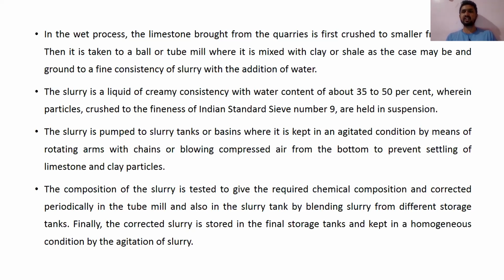Okay, the liquid content in the slurry will be more than the paste. You can understand what I mean to say is slurry. The slurry will be prepared by addition of water into the mix of limestone and shale or clay. Then the slurry is a liquid of creamy consistency with water content of about 35 to 50%, wherein particles crushed to the fineness of Indian standard sieve number 9 are held in suspension.